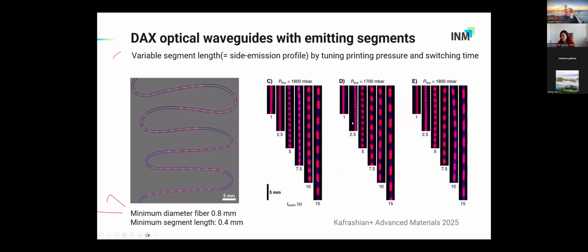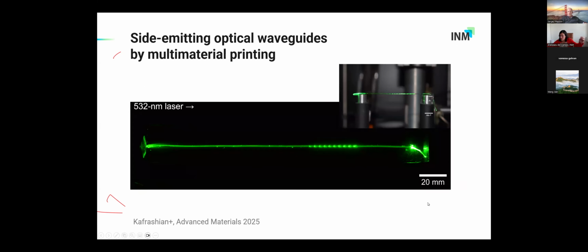And as we saw before, we can change the period. We can change the length of the scattering elements depending on the switching time between the two inks. This is a real waveguide, which is also coupled to a laser. So here we are coupling the laser from this side. You see, these are the waveguided segments. These are the outcoupling segments, which we can place as we want. And here, of course, is the end of the fiber.